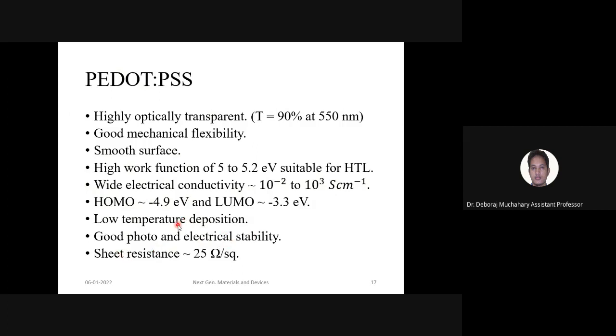Next, what we have is the sheet resistance. We know that as the conductivity is high, the sheet resistance should be low, because these two are interconnected, right? The typical sheet resistance value is around 25 ohm per square. So this comes around 25, hence it is a low sheet resistance.